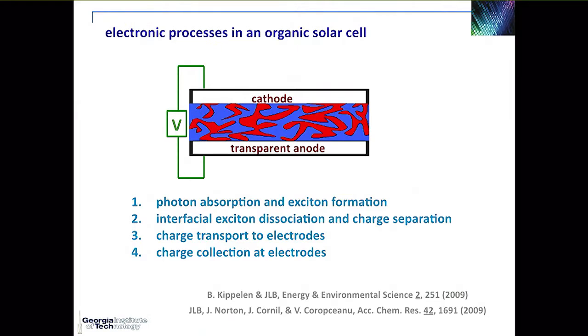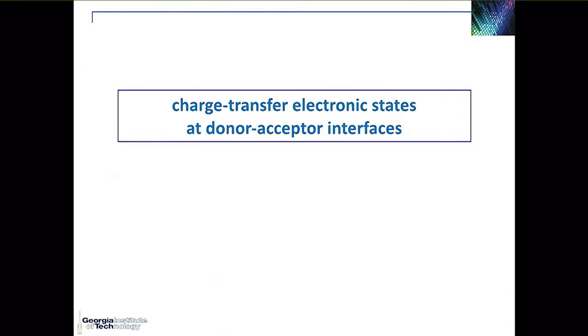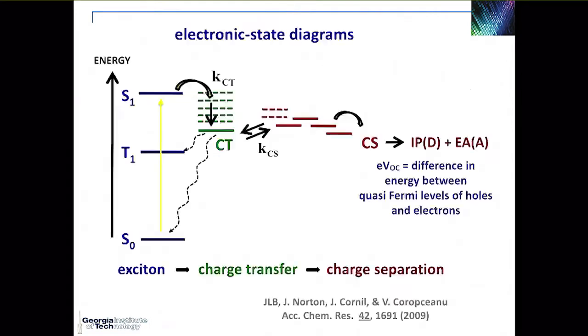So in terms of the electronic processes that need to occur efficiently, you need first to have, of course, strong photon absorption. In the polymer-fullerene solar cells, that absorption comes essentially from the polymer. That leads to exciton formation. At the interface between the polymer and the fullerene, you need to have efficient exciton dissociation and charge separation. Then the charges need to find efficient percolation pathways to reach the electrodes where they need to be efficiently collected. What I'm going to do this afternoon is actually emphasize that exciton dissociation process at the interface between the electron donor and the electron acceptor, and thus the so-called charge-transfer electronic states that appear at those donor-acceptor interfaces.